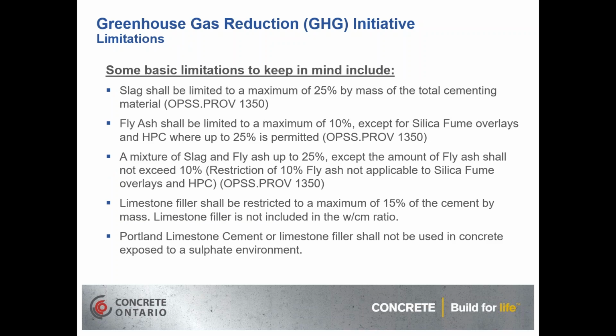Some other limitations to keep in mind. The slag shall be limited to the maximum of 25% by mass of the total cementing material. The fly ash shall be limited to a maximum of 10%, except where we're looking at silica fume overlays and high performance concrete, where up to 25% is permitted. A mixture of slag and fly ash is allowed up to 25% as long as you're not going over 10% with your fly ash. And again, that restriction on the 10% fly ash is not applicable to the silica fume